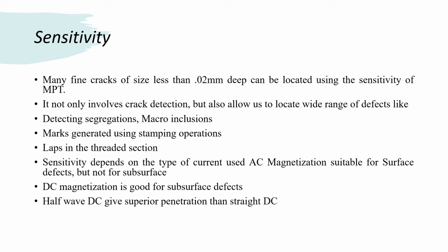In practice, lower levels are quite adequate, and the accepted standard is about 40% of saturation of the material being tested. Sensitivity also depends on the type of current used.